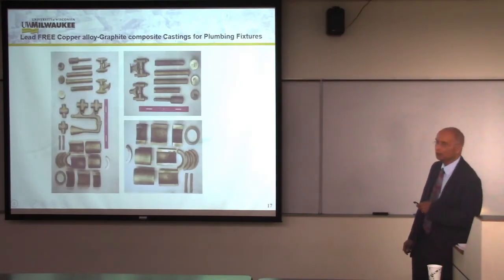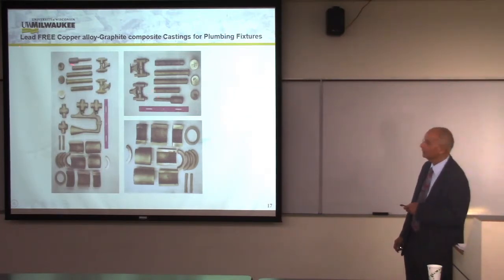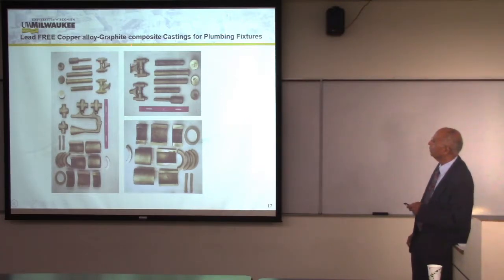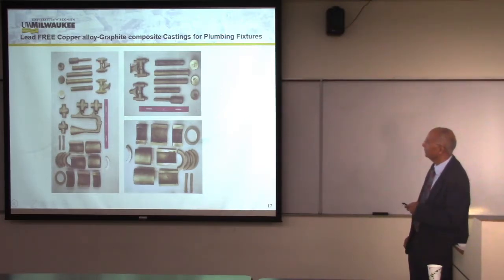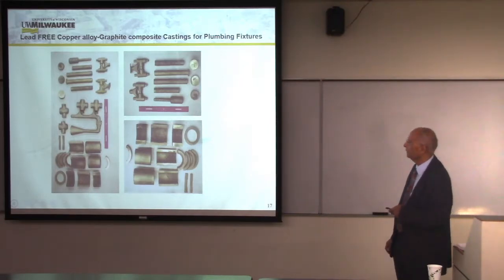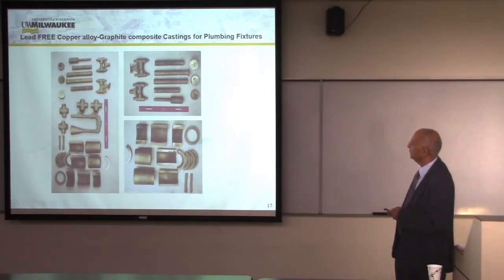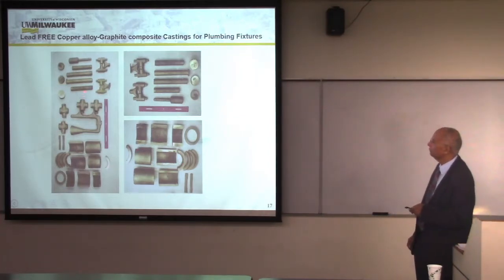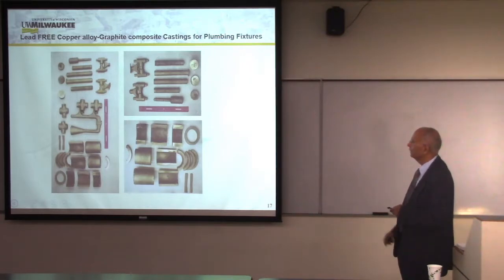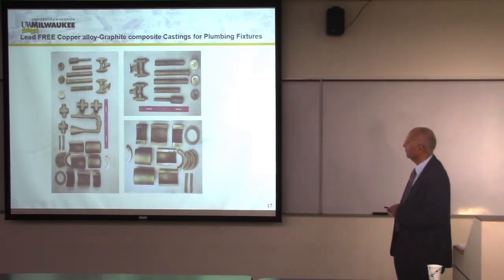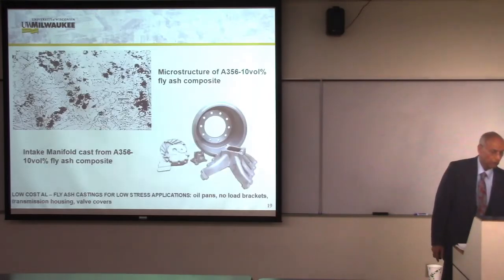I have been talking mainly about aluminum matrix, but there are opportunities in copper matrix composites, and here is an example of lead-free copper graphite composite casting for plumbing fixtures. As you know, lead is being banned in plumbing fixtures because it has deleterious effect on brains. So at our university, we have developed copper graphite where instead of lead, we have substituted lead by graphite and poured that suspension into a variety of plumbing components, and by centrifugal casting, we have concentrated all the graphite so it can be used as lead-free plumbing fixtures and lead-free bearings. I believe there is a great opportunity to manufacture these in India, both for internal consumption where lead is being banned, and also for export to countries where lead has already been banned.